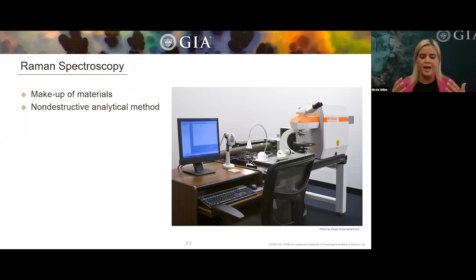So we collect that light, we analyze it, and we're going to produce a Raman spectrum. And this spectrum is then compared to known samples in our database to determine the identity of the material. And this works really well because almost all stones have a distinct Raman spectrum. And Raman can help us with the identification of a rough or an aggregated material if the surface is too rough or the polish isn't clean enough to get a clean refractive index.